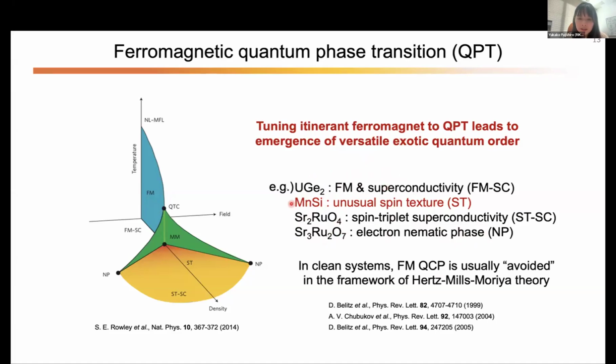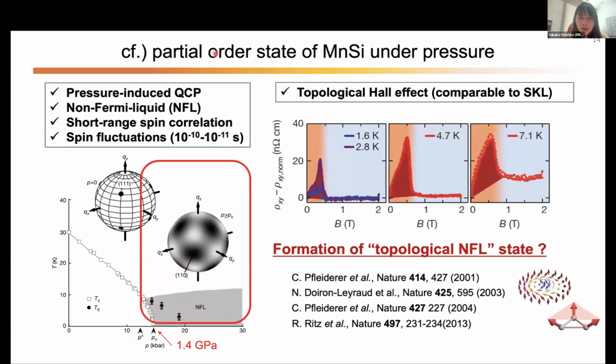And very interestingly, manganese silicide, where the skyrmion was first discovered, has attracted great attention long before the discovery of magnetic skyrmions. This compound has been studied in the context of the ferromagnetic quantum phase transition. More specifically, an unusual exotic magnetic order called partial order state has been discovered under pressure. Manganese silicide has a TC of about 30 Kelvin, and when we apply pressure, the long-range magnetic texture is completely suppressed at about 1.4 gigapascal, and a non-Fermi liquid state emerges above this quantum critical point.